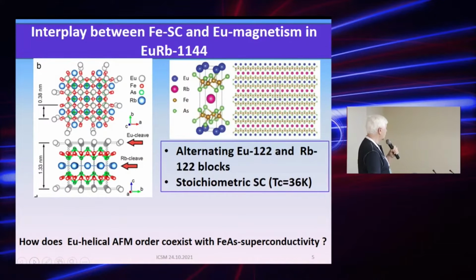First, I show here the crystal structure. This is the top view, and this is a side view. In a side view, you see that the primitive cell consists of two blocks. It's actually alternating europium 122 and rubidium 122 blocks, and they are put on top of each other. And therefore, because of the different intrinsic primitive cell size, they should be intrinsically deformed, and this may be the reason for the superconductivity to happen with no doping.